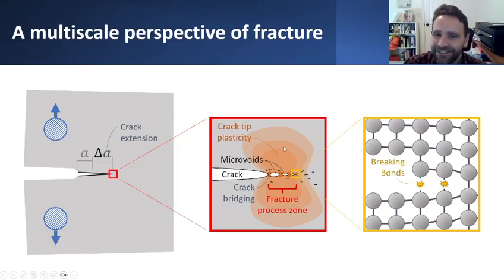But that excessive plastic deformation and changes in the material microstructure will further lead to other things. At some point the material will simply fail to sustain the ability to deform plastically in the vicinity of this crack tip. And you might start to see little micro cracks develop throughout the material. They might not be very big to begin with, but eventually those micro cracks will start to grow and develop almost voids or empty space in the material called micro voids. And as those micro voids continue to grow and separate, you might get even more localized plastic deformation, and you might have this kind of crack bridging behavior where small strands of material draw out almost and try to bridge the connections between the crack until eventually they coalesce. These small bridges break, and then finally you have whole-scale crack extension.